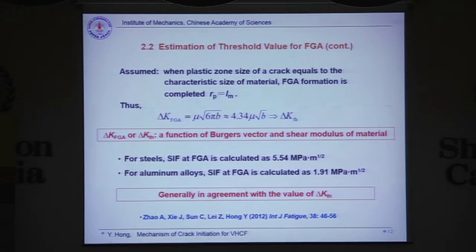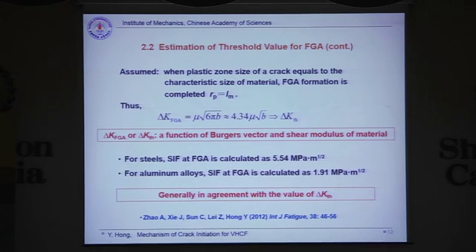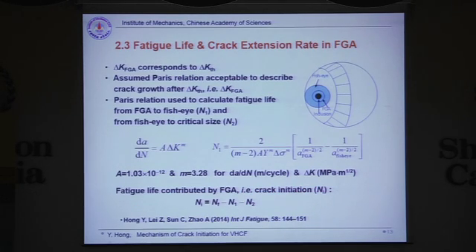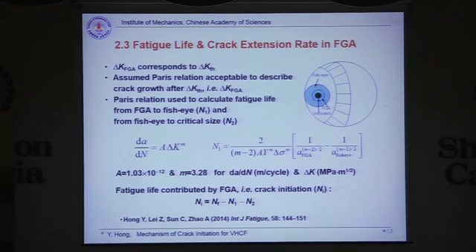So, for this equation, we get the result for steels of 5.5 megapascal square meter. It's in quite good agreement with my previous slides of 4 and 6 megapascal square meter. Then I will show you the estimations of fatigue life and the crack extension rates within this small range.